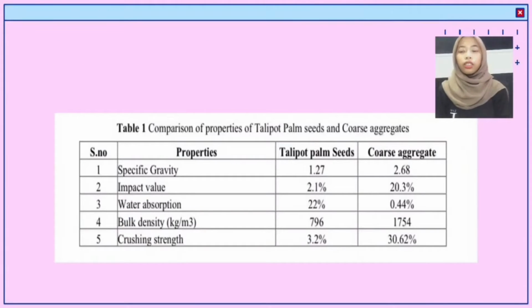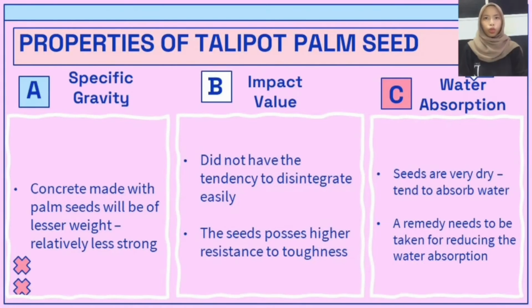So, here is the comparison of properties of talipot palm seeds and coarse aggregate that have been tabulated into the table data. As we can see here, the specific gravity of the talipot palm seed is less than coarse aggregate. For the impact value, the coarse aggregate got the highest percentage, while for water absorption, the highest is talipot palm seeds. The bulk density is highest for coarse aggregate, and for the crushing strength, the highest percentage is for coarse aggregate.